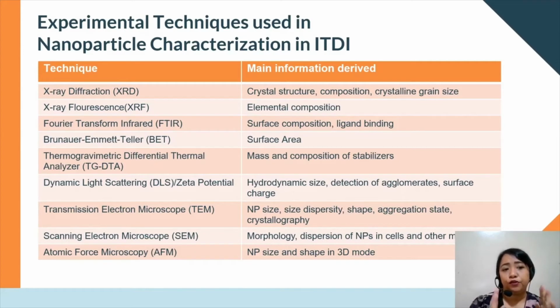So first, on the left column, we have the technique, and on the right column, we have the main information derived from these techniques. For X-ray diffraction or XRD, we can get the crystal structure, composition, and crystalline grain size of a material. For X-ray fluorescence, we can identify elemental composition. For Fourier transform infrared, we can identify surface composition and ligand binding. For Brunauer, Emmett, Teller, or BET, we can measure the surface area of particles.